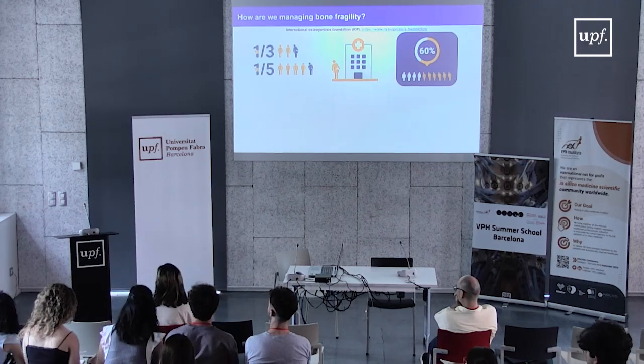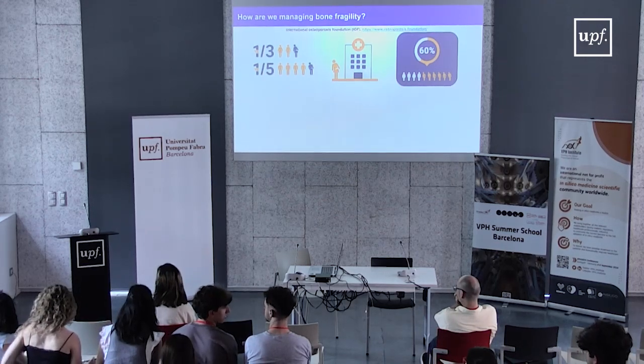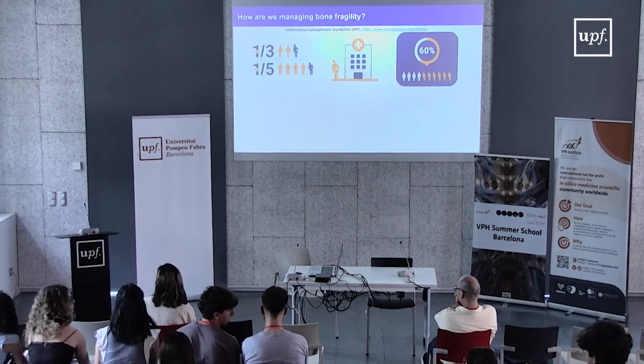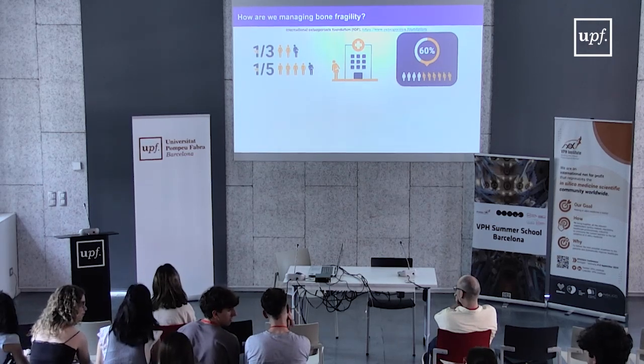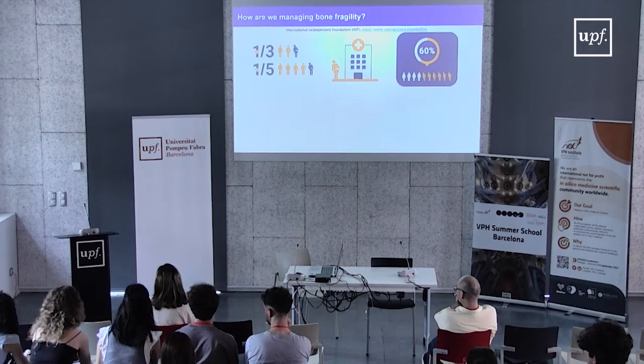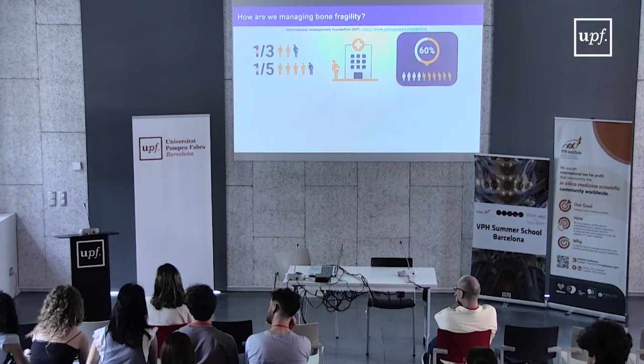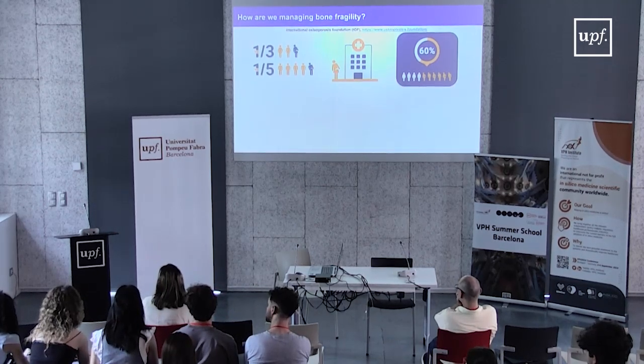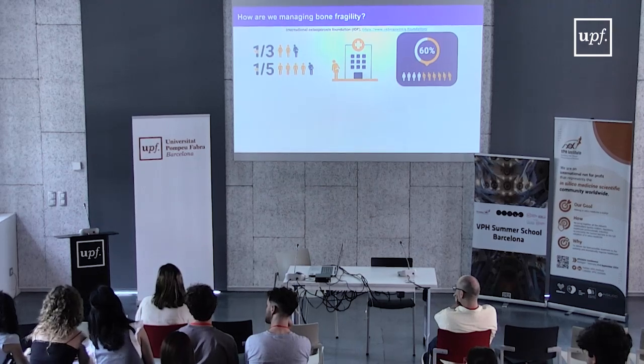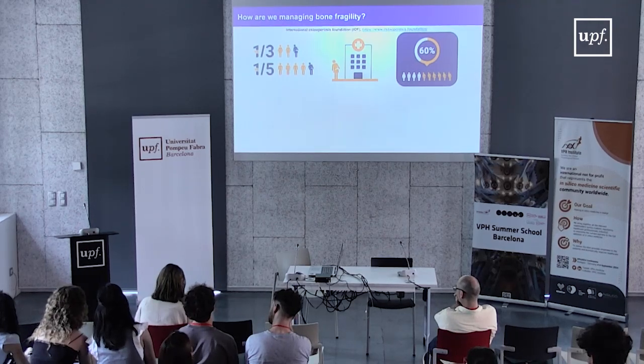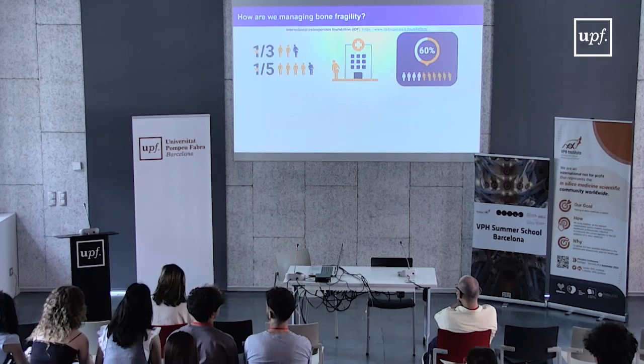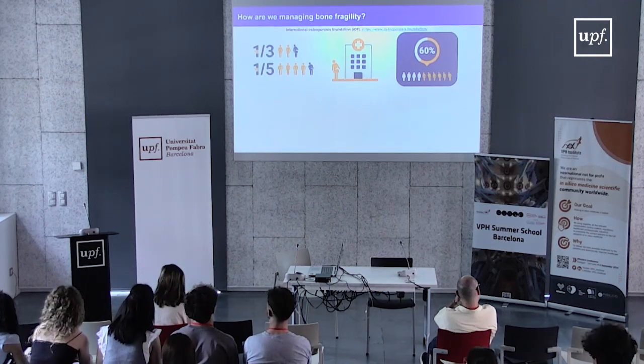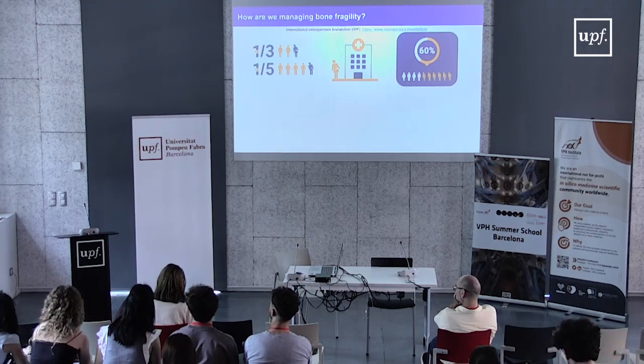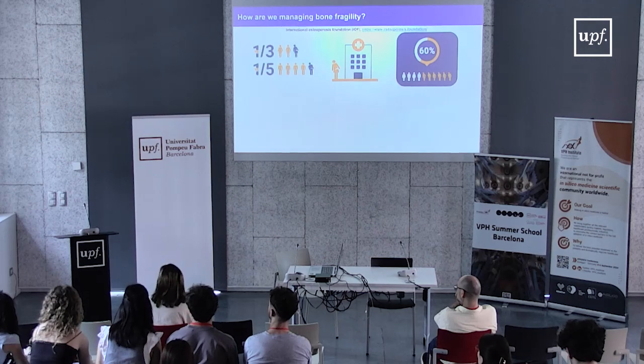No, when it happens to elderly, it's really a complex problem, and almost 25% of patients with a femoral neck fracture after 65 years old won't survive 1 year. So 25% of patients will die after a hip fracture. And 60% of the patients that will have any osteoporotic fracture will require assistance a year after their fracture. Even if the fracture actually stabilizes and they rebuild bones, there is no sign of the fracture, there is a loss of independency.